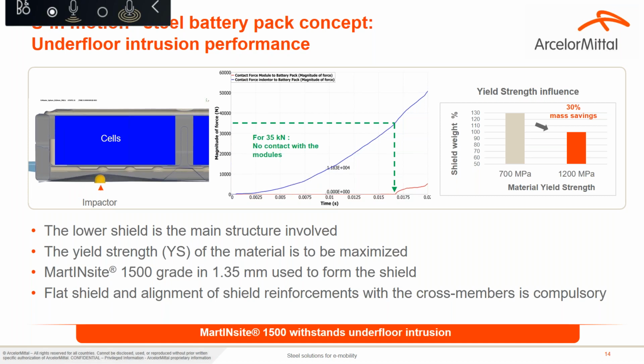The second one we found that was very important: it's to have a flat, completely flat shield. It's not so obvious to have a flat part in automotive, but in this case, if you want to take the best from the yield strength of your material, you have to push directly on your material, and so to be very flat.